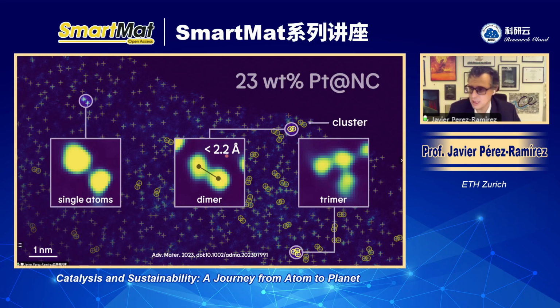And that means they must be forming a dimer. And this is actually a trimer. What you see over here, this is a trimer. Again, the distance between this and this platinum atom is smaller than the platinum bond distance. That means now that the algorithm is smart enough not only to detect metal species, but also tell you what's your degree of clustering in the sample, which in a way reflects how successful your synthesis was of single atom catalyst.